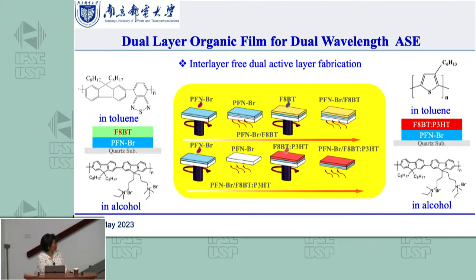But it's doable. We tried. Look, we used this alcohol-soluble one and F8BT, which we dissolve in toluene. The spin coating is very easy: deposit the first layer and leave it to dry for a few minutes, or just put it on a hot plate for a few minutes. Then you deposit the second layer, and you have made a two-layer material.